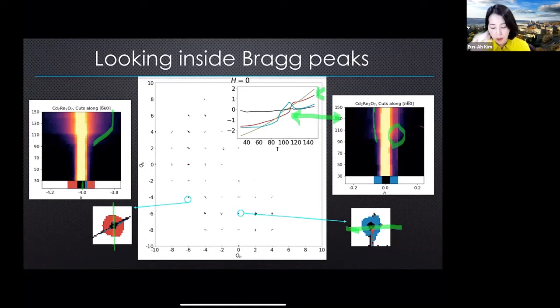Data is right. But it occurred to us that this makes sense. Why does it make sense? Well, one of the candidate order parameters that we were considering was a two-dimensional order parameter. Two-dimensional order parameters have a Mexican hat. There has to be a Goldstone mode if it indeed had a two-dimensional order parameter with a weak symmetry breaking field. And by tracking down the selection rule of when we see this fluctuation and when we do